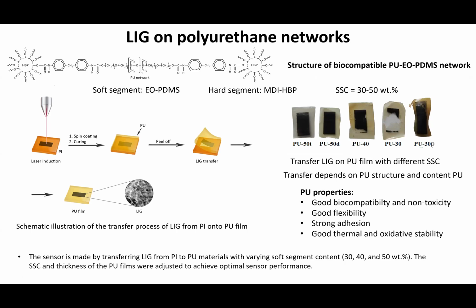So leaving behind PDMS-based devices, we set out to make graphene on polyurethane networks. This is a different class of polymer now that contains a soft segment and a hard segment. You can see that on the top is these long molecular chains. And then we can vary the ratio of the soft segment to the hard segment, and by doing that, tune the properties of the LIG, which is what we did.